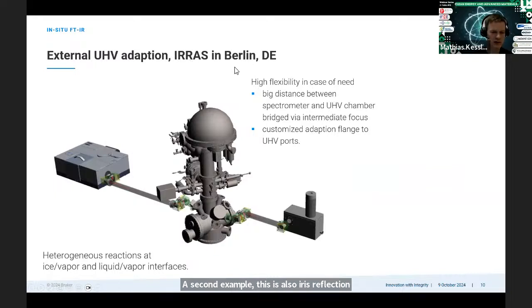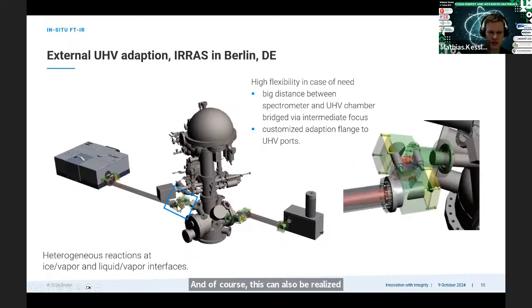This is used to investigate reactions on ice, vapor, and liquid vapor interfaces in a reaction chamber. And in this installation, we have to bridge very long ways from the spectrometer to the chamber and to the FTIR spectrometer and also to the detector chamber. And of course, this can also be realized. And for that, we use an intermediate focus at 2 positions. And with that, we are able to use a very long beam path to access then our UHV chamber.